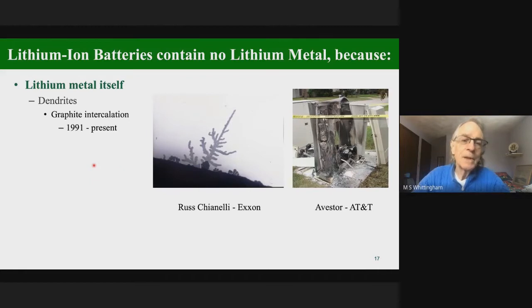This is a typical lithium battery. This is showing lithium metal itself, and this is work of a colleague of mine, Russ Chianelli, back from the 70s. When you plate any metal out, you tend to get dendrites formed, and this is what a dendrite is. The reason is that as soon as you get a little protuberance, like we show here, the voltage drop, or the field, from this point to the other electrode over here is higher. So once this starts, it keeps on going. And you get the formation of these dendrites that then puncture through what would normally be a separator separating the two electrodes. If that happens, you get a battery short, and you can see you burn out the battery.